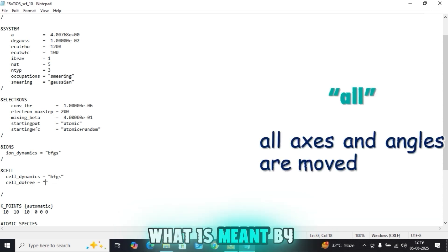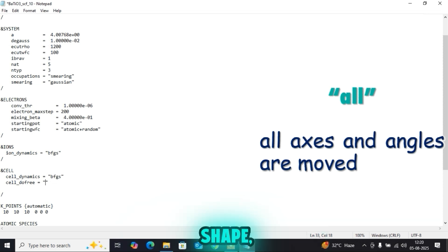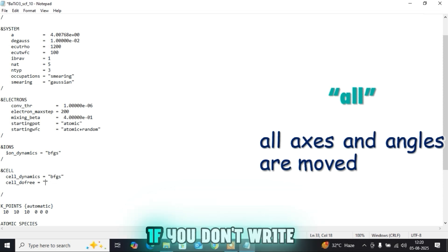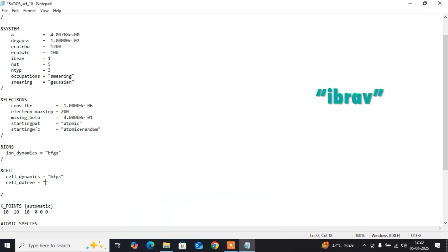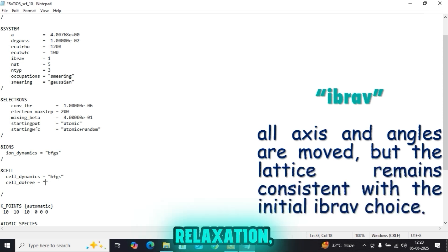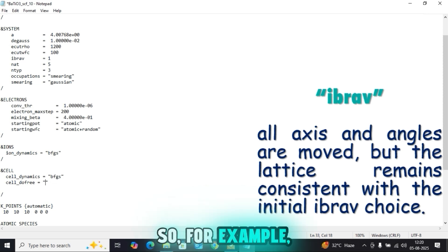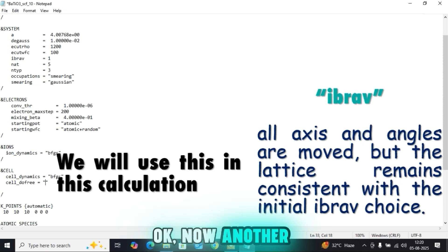For cell_dofree there are several options. First, you can write 'all', which means that while doing the vc-relax calculation the volume, shape — everything — may vary. It will go to the minimum energy structure by varying anything possible. If you don't write anything, 'all' is the default. If you write 'ibrav', it means everything will change but your Bravais lattice will remain constant. For example, if you have a face-centered cubic it will remain face-centered cubic.